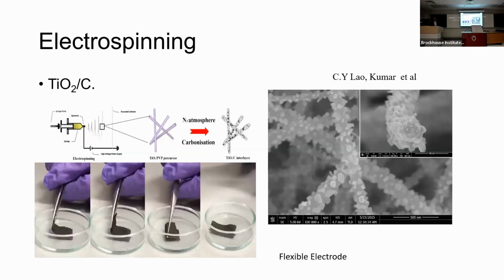And such a material can be very easily made as well. It is done by electrospinning, for example. You combine polymer with the titanium oxide and pyrolyze it, and you end up with this structure. And this structure you can see is highly flexible as well. So therefore, in the flow system, it's not a rigid structure, so it's not going to break.